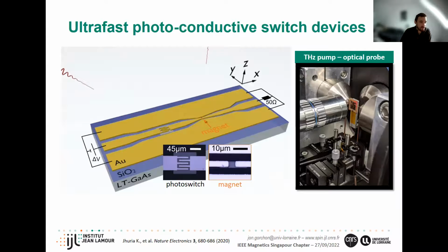This is a bit more unusual technique that we're using. So we use these photoconductive switches here. The way this works is that you put a bias around them. It's a semiconducting material that is almost insulating at rest, and when you irradiate with light, you short circuit the circuit. You change the conductance, and so you can release a pulse. And because the lifetime of the carriers in the material is very short, it very quickly opens up again, and so you get a very short burst of current.